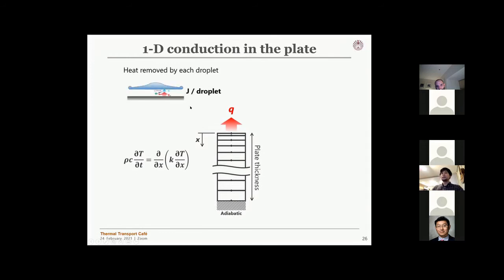We can estimate the heat removed by each droplet using a particular model, giving the units joule per droplet. We multiply this by the number of droplets per unit area and unit time, which is basically the spray condition. If you multiply these two parameters, then we can get the heat flux at the surface.